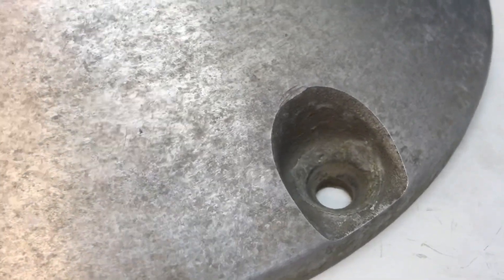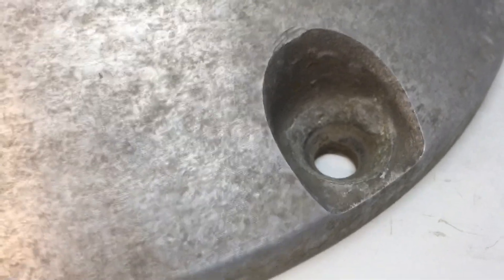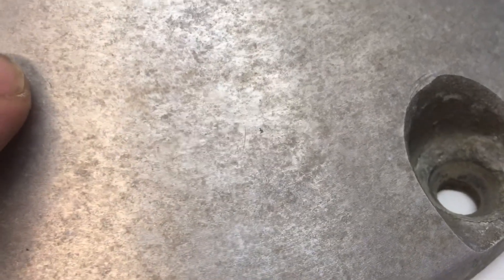Now this entire piece has been cleaned off and wiped dry with regular paper. What we see here is aluminum hydroxide and aluminum oxide has formed to different extents over the surface with time. Some areas where you have had more salt water spray, you have more oxides formed. In order to transform this into this, it's not enough to just remove the oxides because you will still have an uneven appearance. We are going to etch this and completely oxidize the surface evenly, and then we will remove the oxide with acid so that we can get this even appearance.